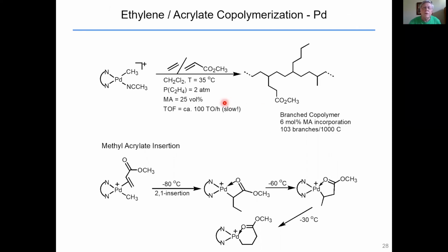It turns out you can do this. So you can take one of these palladium species and copolymerize ethylene and methyl acrylate. If you use a lot of methyl acrylate, you can get up to 6 mol% incorporation into the copolymer, but the turnover frequency is quite low. And one of the reasons for this, so this is very slow, it turns out you can see this pi complex by NMR at -80. You can watch it undergo migratory insertion.